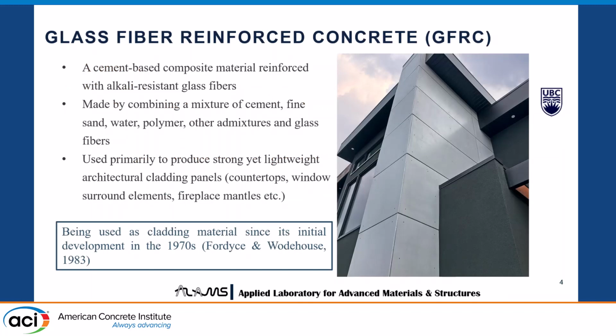It's basically a cement-based composite material which is reinforced with glass fiber, usually the alkali-resistant ones, and it's actually made by combining a mixture of cement, then fine sand, then water, polymer, and some other admixtures, and obviously glass fibers. And it has different uses, but it's primarily used for producing lightweight yet strong architectural cladding panels. It is also used for countertops or window surround elements, and sometimes for fireplace mantles. And GFRC was developed in the 1970s, and since then it is being used as a cladding material.